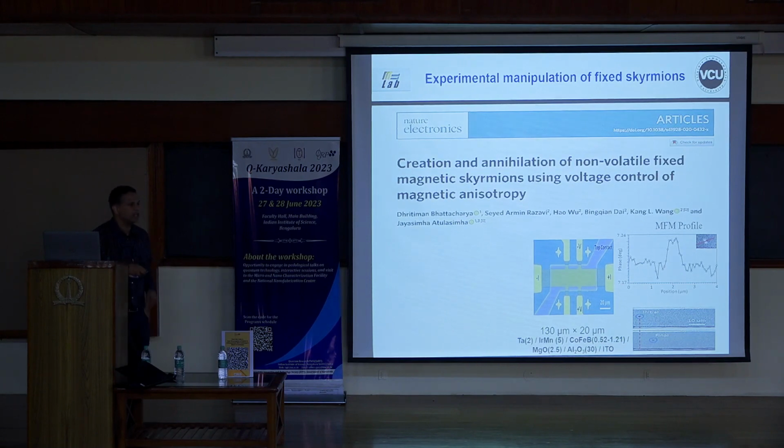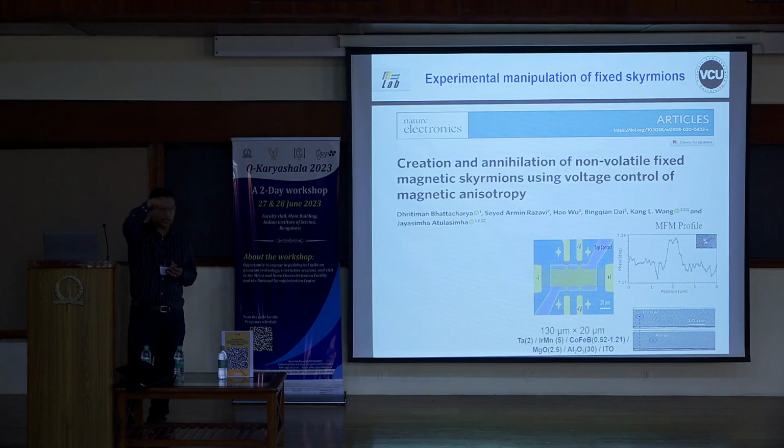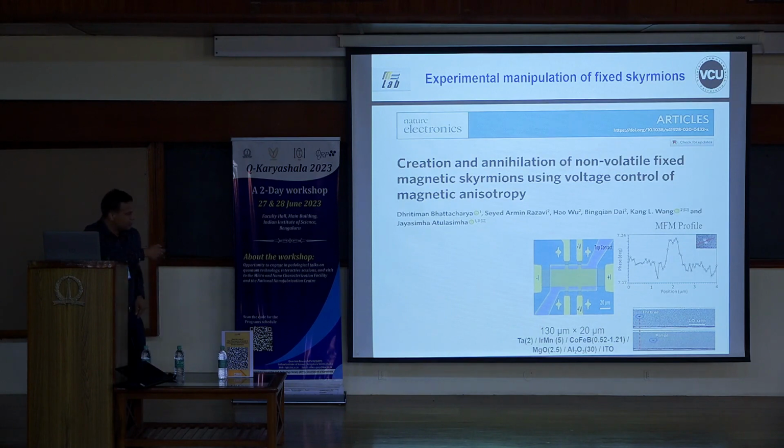The way you prove it's a skyrmion is you go with a magnetic tip that is oscillating. If you have looked at an AFM, it taps, taps, taps, tells you the topology, it lifts up and then taps again, and then the magnetic field, whether it's like this or like this, will make a difference to your tip depending on the way you magnetize the tip. From there, you can actually map and say, if I go near a skyrmion, this is the stray field at 40 nanometer height from the skyrmion as I go across, right? And we can prove that we get that very exotic state at room temperature in a stable way where you can do multiple scans.